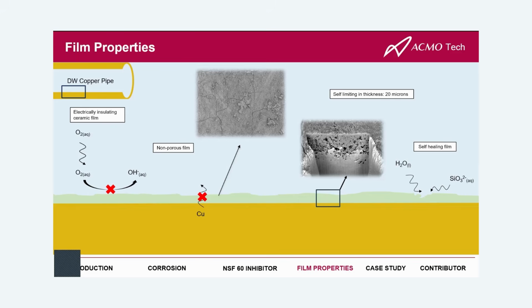piping. Now, because you're forming a film, you may wonder, is the film going to restrict flow or cause scale or anything like that? Well, the technology has been well refined, and basically we've calculated that this film is self-limiting in thickness, and the thickness that it grows to, this is a 2-year-old sample, is 20 microns. So to put that in context, that's about the same thickness as one strand of silk. So it's a very, very thin film. It's not going to continue to grow on itself. And that's because it actually needs corrosion to happen in order to grow.